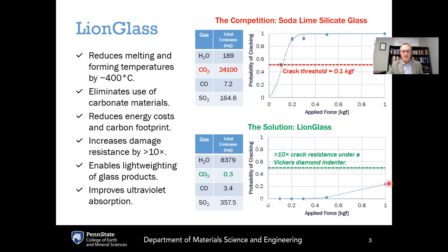This translates into improved scratch resistance and improved breakage resistance. Another advantage of the improved mechanical properties of LionGlass is that this can be traded off to enable light weighting of glass products — reducing the wall thickness of glass jars, bottles, and so on. This further reduces the carbon footprint of glass manufacturing since less energy is needed, less batch materials are needed, it also improves manufacturing throughput, and it improves downstream costs and environmental impact from transportation if you have lighter weight products.